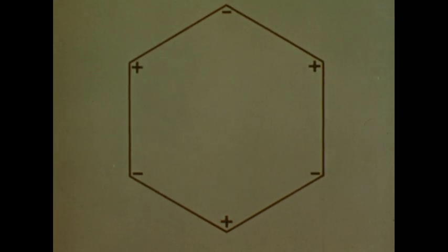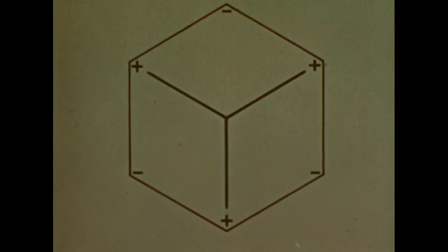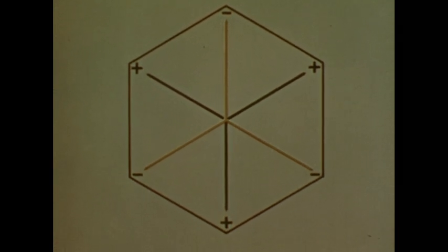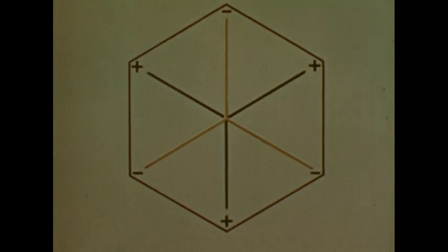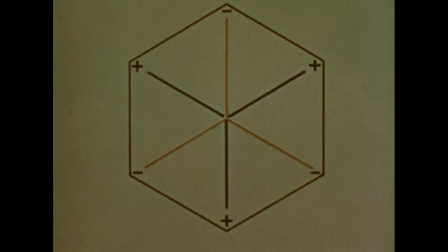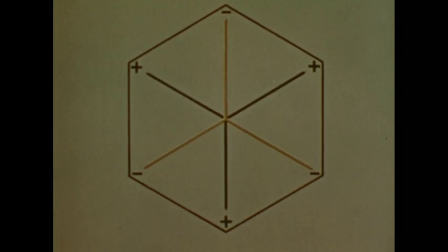Since the piezoelectric charge in these three directions is positive, and in these three directions is negative, there must be a corresponding difference in the structure in those directions. That is, the arrangement of the atoms must have threefold symmetry. The piezoelectric effect is just more sensitive to the difference than the growth of the crystal is.